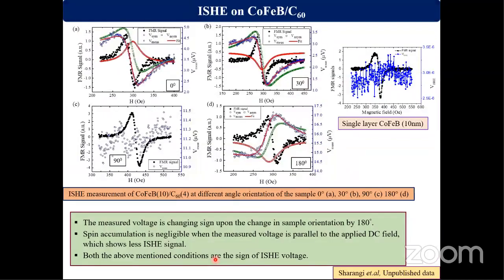So ISHE on the cobalt iron boron C60 samples. Here we have performed ISHE on the cobalt iron boron C60 4 nanometer sample. This figure A is ISHE at 0 degree, and B is ISHE at 30 degree. This is ISHE at 90 degree, and this is ISHE at 180 degree.